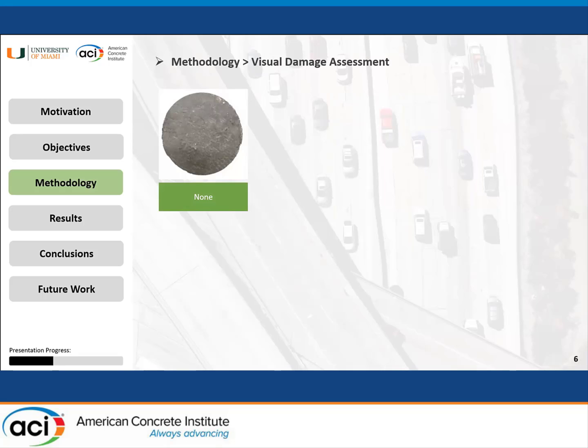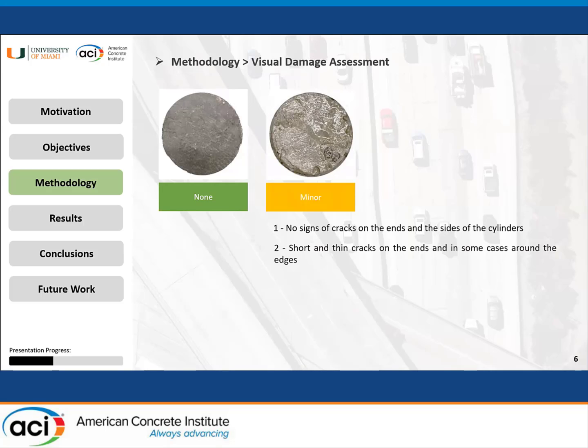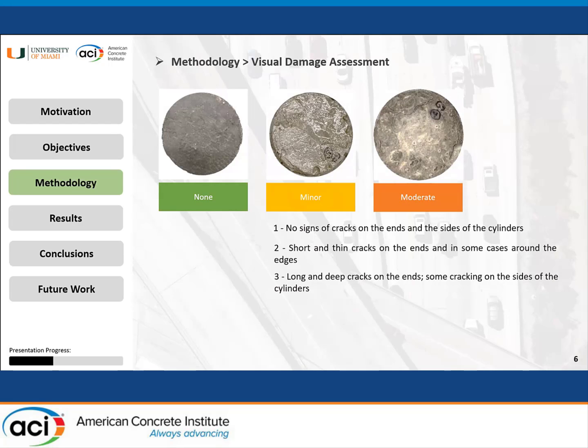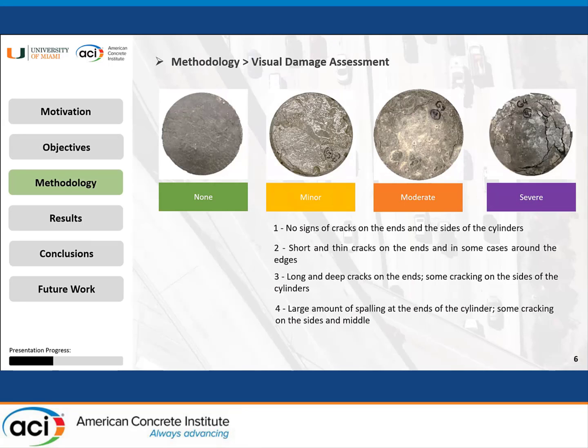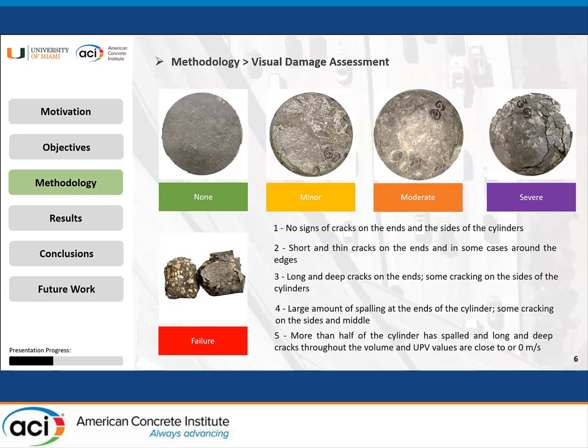In order to have the visual damage which was expected to happen in our concrete cylinders classified and tracked over time, we created this visual damage classification, starting with none, when no signs of cracks on the ends and sides of our concrete cylinders were seen. Then we had minor, when short and thin cracks on the ends and in some cases around the edges of our concrete cylinder were observed. Then we have the moderate classification, which is when long and deep cracks on the ends and some cracking on the sides of the cylinders were observed. Then we have the severe, which is when large amounts of spalling at the ends of our cylinder and some cracking on the side and the middle section of our concrete cylinder is observed. And then, of course, we have the failure, which is when more than half of the cylinder has spalled and there are long and deep cracks throughout the volume, and the UPV values, which are going to be measured, were around 0.